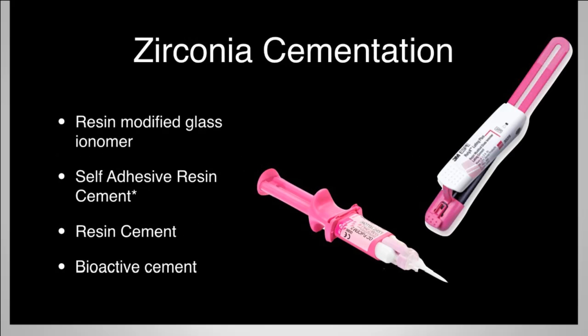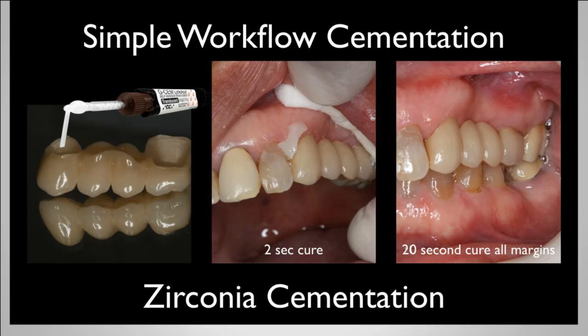So if something is naturally retentive, I offer a resin-modified glass ionomer. So something like Fuji Cem and/or RelyX Luting Plus is, I think, a great cement of choice. You can also use a bioactive cement, like a Ceramir type cement, which will work well in this category. On the other hand, if I don't have proper retention, or I have maybe something less, I'll opt for a self-adhesive resin cement. So in this 4-unit bridge case, I knew there was going to be a little higher load being placed here. Our canine preparation was a little bit shorter than I hoped for. So we used G-CEM LinkAce in this case. It was easy to clean, went to place, light activated, or light accelerated I should say, and we were able to get this in place with really no issues.